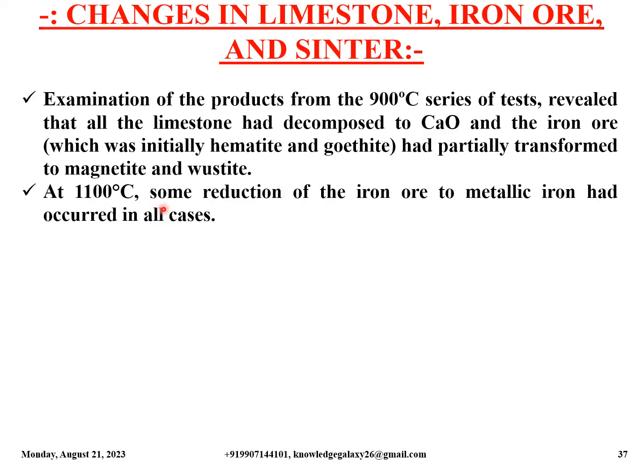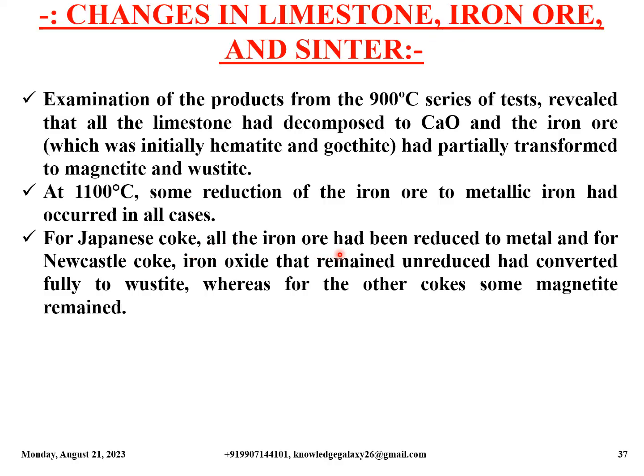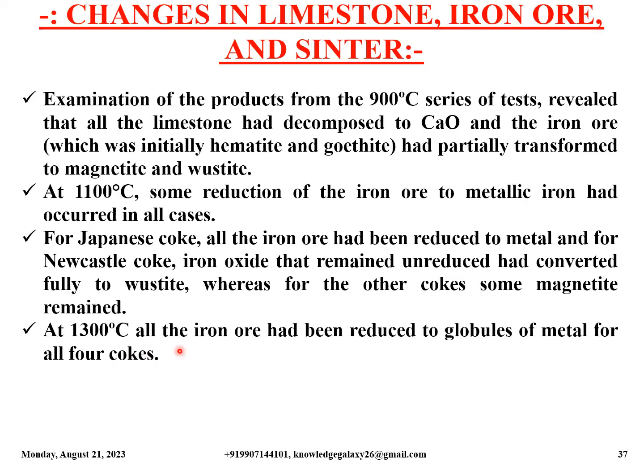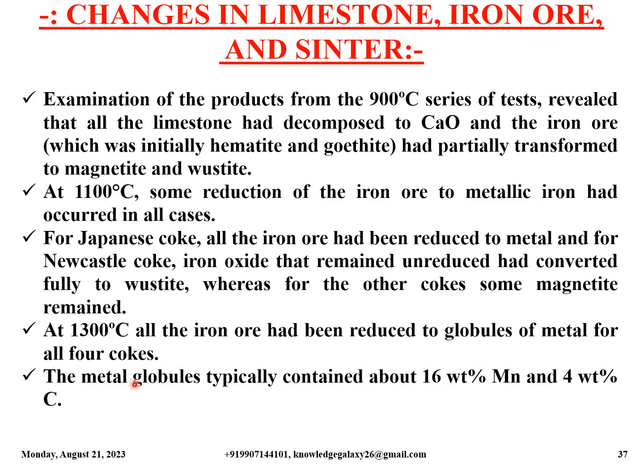At 1100 degrees Celsius, some reduction of the iron ore to metallic iron had occurred in all cases. For Japanese coke, all the iron ore had been reduced to metal, and for Newcastle coke, iron oxide that remained unreduced had converted fully to wustite, whereas for the other cokes, some magnetite remained. At 1300 degrees Celsius, all of the iron ore had been reduced to globules of metal for all four cokes. The metal globules typically contained about 16 weight% manganese and 4 weight% carbon.